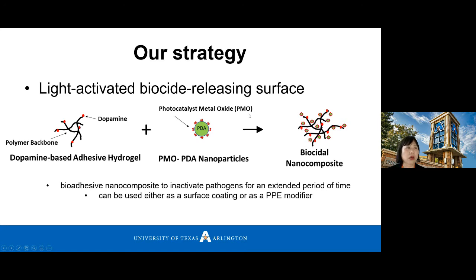And together with this material, we develop a photocatalytic metal oxide, or PMO. So what does this nanoparticle do? You can use light to activate it, and then it will release reactive oxygen species. It will release something that can inhibit the growth of the pathogen. So it can kill the virus and the bacteria when you shine the light. When you mix this with the hydrogel, we produce a biocidal nanocomposite. This nanocomposite will adhere on the surface, and when you shine the light, it will inactivate all of the pathogens on the surface for a long time. So we can use this as a surface coating or as a PPE modification.